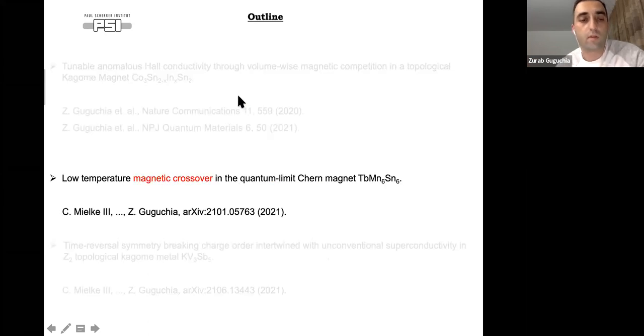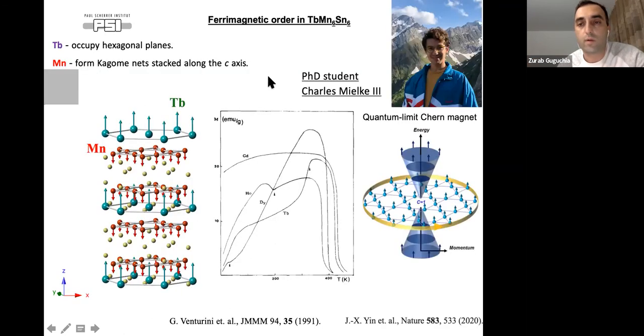Okay, now the second part of my talk is about this low temperature magnetic crossover in this terbium-166 kagome system. This is a project of my PhD student at PSI. Different from the cobalt compound, here we have two magnetic sublattices, terbium and a pristine manganese kagome lattice. And back in 91, it was shown that the system has a high magnetic ordering temperature and some spin reorientation at around room temperature. So it is kind of a room temperature magnet.